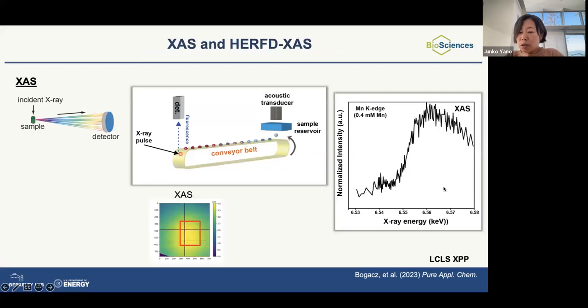So this is the data we got from the traditional way of doing absorption spectroscopy using this setup. We put the detector up here, and using the water ring intensity, we collected data. From 0.4 millimolar manganese, the data collection with the 120 hertz X-ray pulse took about 1 hour to get this data, which is not too bad, I would say. There is a hope to get cleaner data by collecting longer.